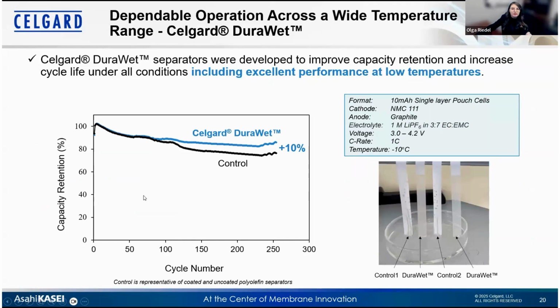As mentioned, we also see this advantage of increased electrolyte retention at low temperatures. So here you see some cycle data of DuraWet versus a control at -10 degrees C. Since the viscosity of the electrolyte is increasing at low temperatures, the electrolyte starts to be pushed out of the pore structure slowly. And this you can see by the control dropping in capacity. Our DuraWet separator maintains a 10% higher capacity retention at 250 cycles in these examples. So DuraWet is really your solution for dependable operation across a wide range of temperatures.